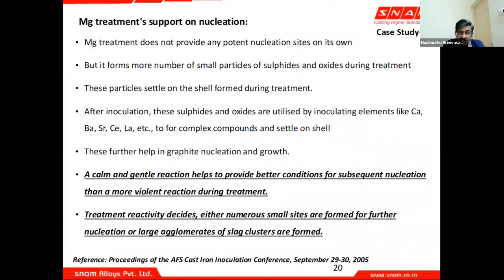Magnesium by itself will not provide any potent nucleation sites, but it forms all these small particles of sulfide and oxide. And then, as I told you, the sulfides of barium, cerium, lanthanum. This mentions strontium because there are some ductile iron foundries which also use strontium-based inoculant and are able to get results. Though we say that calcium nullifies the effect of strontium, we have seen that some foundries are buying a strontium-based inoculant and they are able to successfully use strontium.